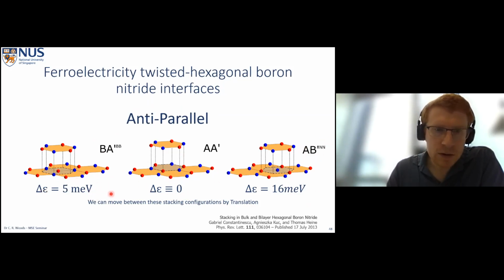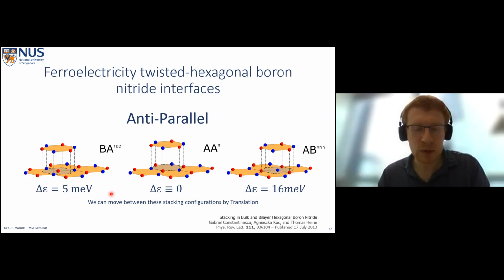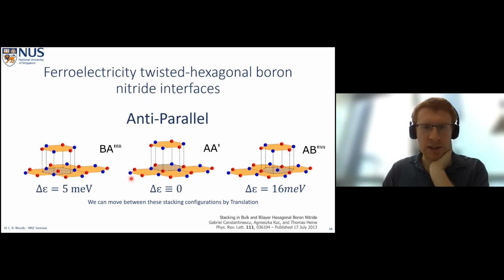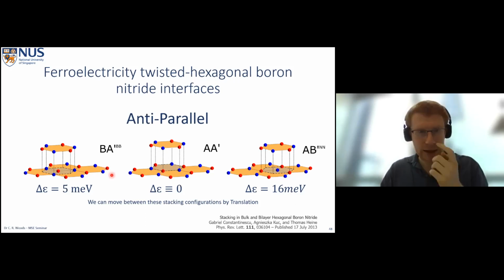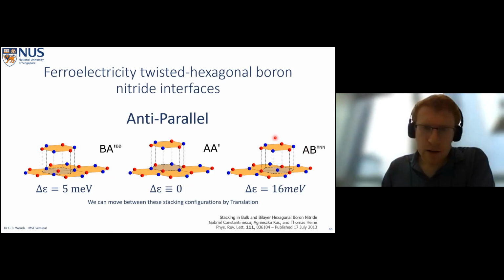And these stacking configurations have higher energies. So they have less binding energy, so they're less energetically favorable. And this can be understood in terms of just lattice binding, because if we have polar molecules here, we have positive and negative charge likes to sit near each other. So it's just a simple case of lattice binding, as well as some van der Waals contribution too.